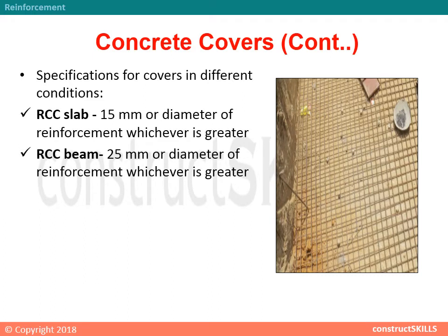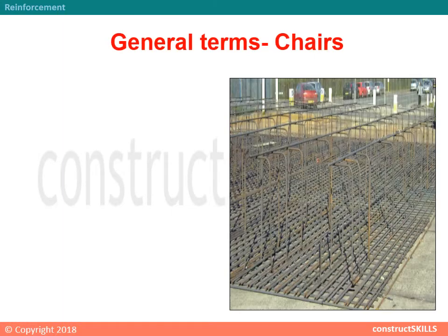RCC slab: 15 mm or diameter of reinforcement, whichever is greater. RCC beam: 25 mm or diameter of reinforcement, whichever is greater. RCC column: 40 mm.